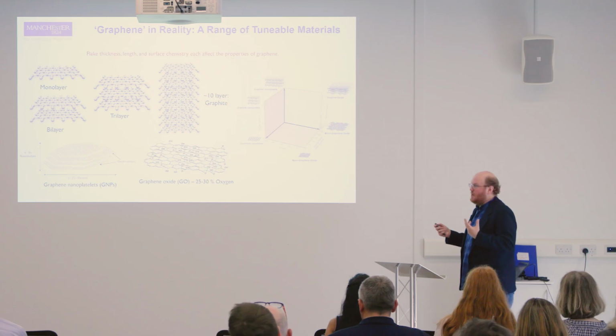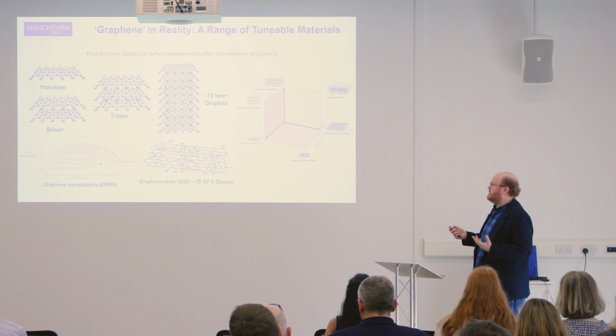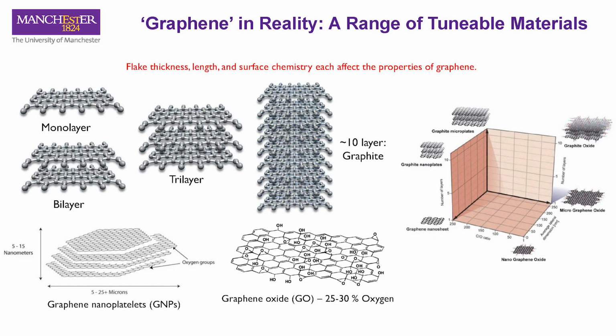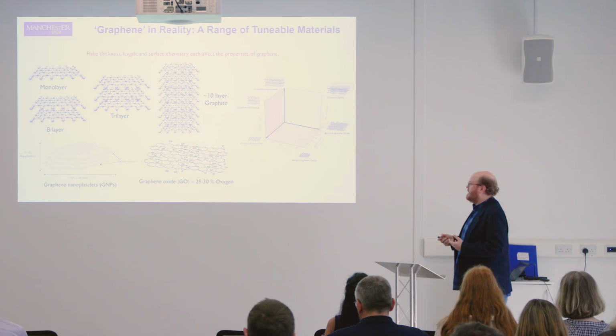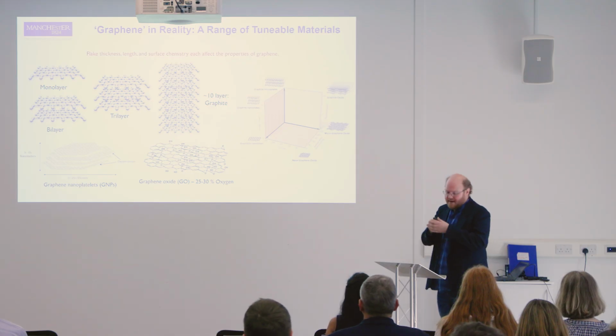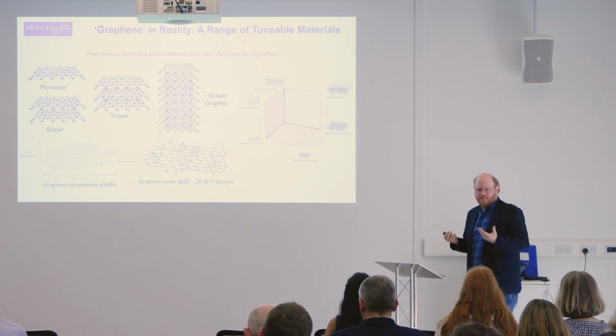So what that means is we really have this very large parameter space where we can look at the properties of the material that we're using for a given application. You've got the lateral size, the carbon to oxygen ratio, the thickness, the number of layers, and that gives us a wide variety of materials, which again, colloquially or even commercially, might all be referred to as graphene, but the wrong material is going to give you the wrong results. So if you're adding graphene oxide to try and get electrical properties, it's not going to work. You're adding an insulator. The same as if you want good mechanical properties and you're adding very, very small flakes, that's not going to give you very good reinforcement.